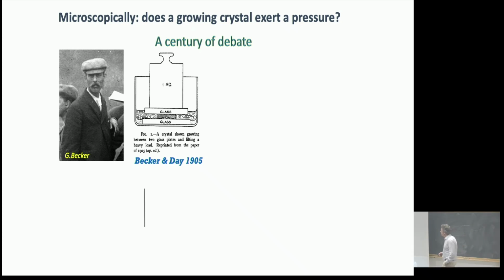Yeah, and so the question whether a growing crystal can actually exert a pressure is a very old one. It's been more than a century of debate. And there are very lovely experiments where people have tried to grow salt crystals between two plates, putting a weight on the salt crystal and trying to see whether the growing crystal would actually push up the weight. And the answer is absolutely not trivial. And PowerPoint is absolutely not trivial either.